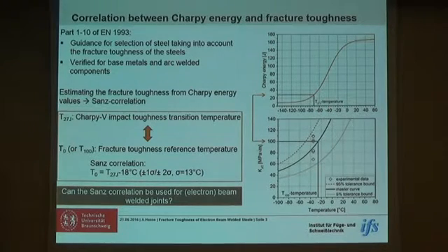So the Sanz correlation reads as T0 is T27 Joule minus 18 degrees, and depending on the literature you use, you find either 1 sigma or 2 sigma deviation, with sigma being roughly about 13 degrees. And we asked ourselves, can the Sanz correlation be used for electron beam welded joints as well?